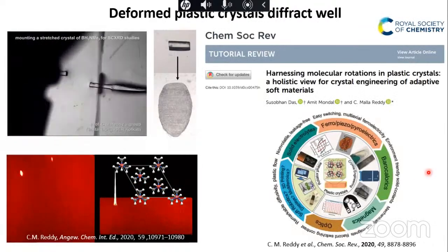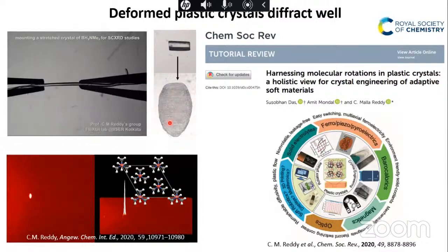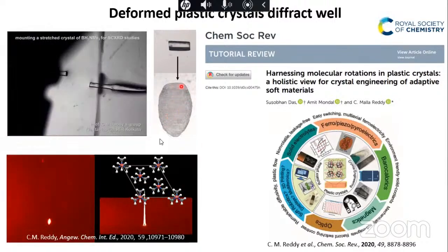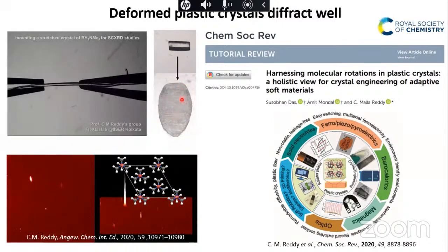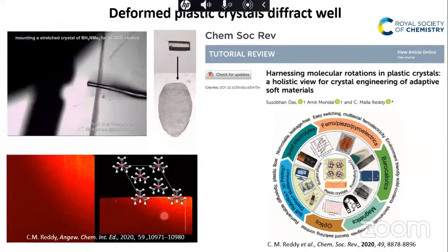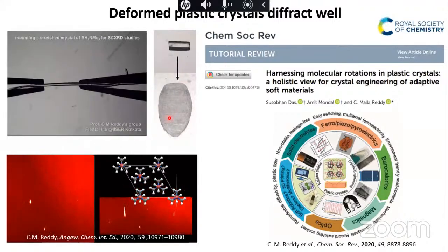And even after making a thin film like this, with around a 100-200% increase in size, when we took a good portion from it and diffracted it, we could still get the single crystal structure from these crystals. This is very, very unusual for molecular crystals.